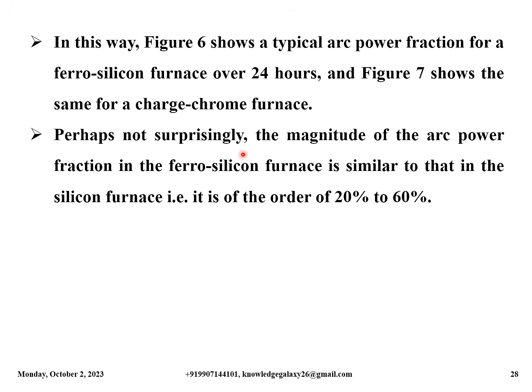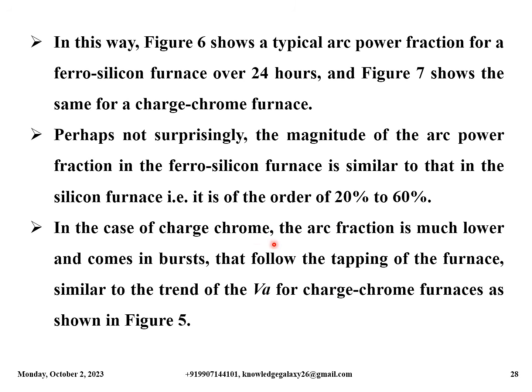Perhaps not surprisingly, the magnitude of the arc power fraction in the ferrosilicon furnace is similar to that in the silicon furnace, that is, it is of the order of 20 to 60%. In the case of charge-chrome, the arc fraction is much lower and comes in bursts that follow the tapping of the furnace, similar to the trend of the VA for the charge-chrome furnaces as shown in figure 5 above.